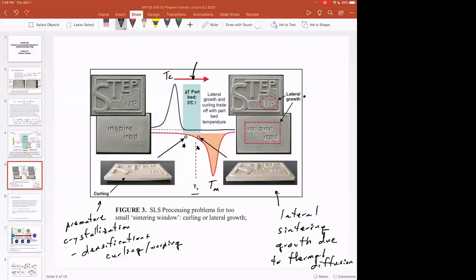And so this is where optimization of the bed temperature and the laser power really comes into importance, is you have to balance these different factors in order to get the resolution you want, and you don't get over melting versus curling of the part or some sort of unsuccessful build. So again, this sort of lays out the basic framework for how to think about these problems, but of course, depending on exactly the machine you have and exactly the powder you have and the thermal conditions in the instrument, it's going to take some optimization to nail down all these different factors. Any questions on this?